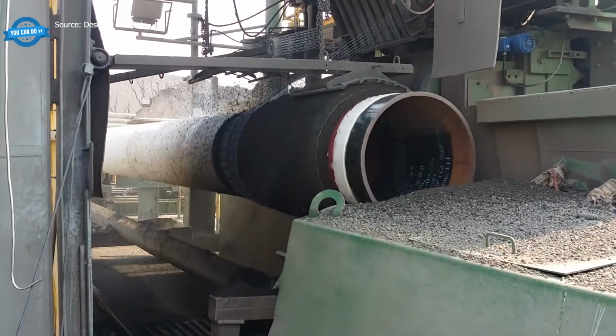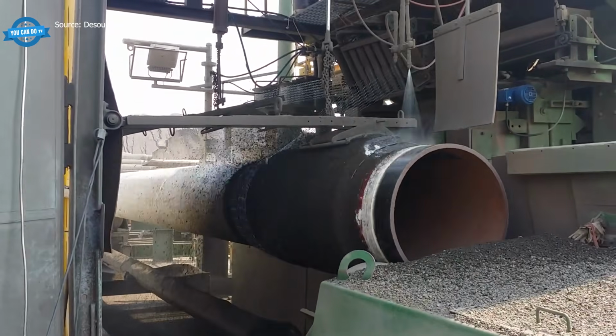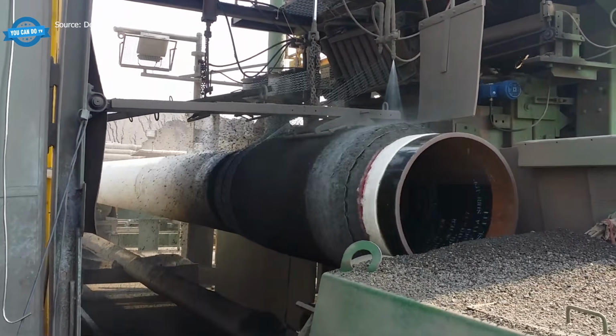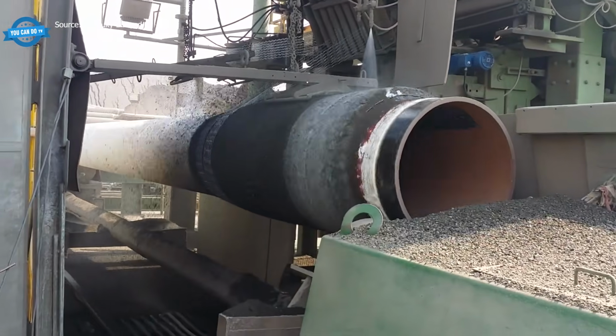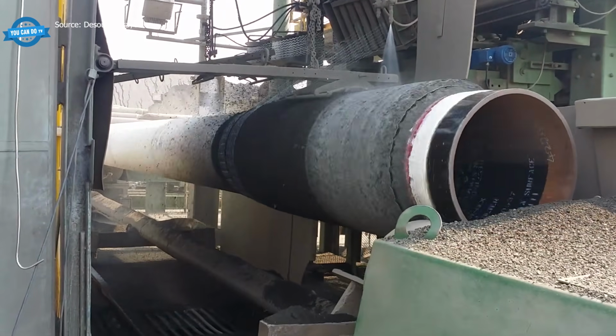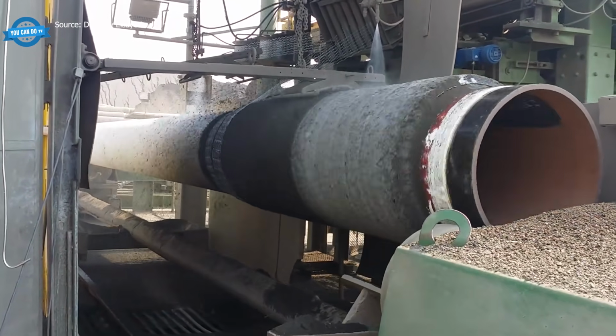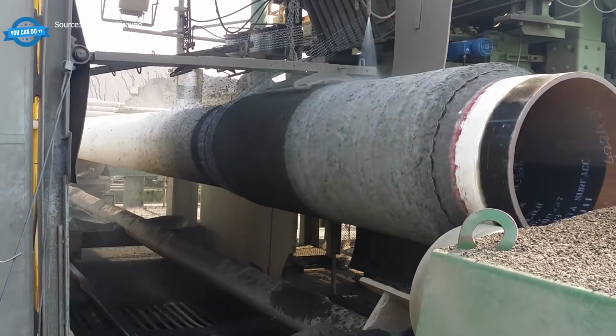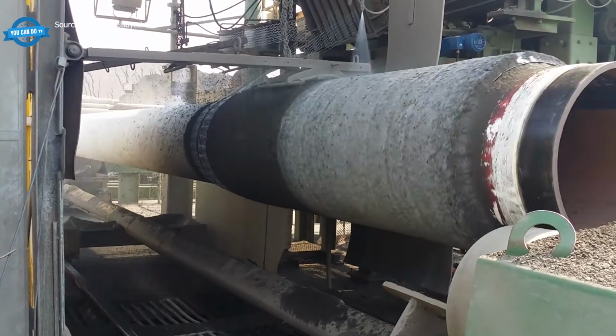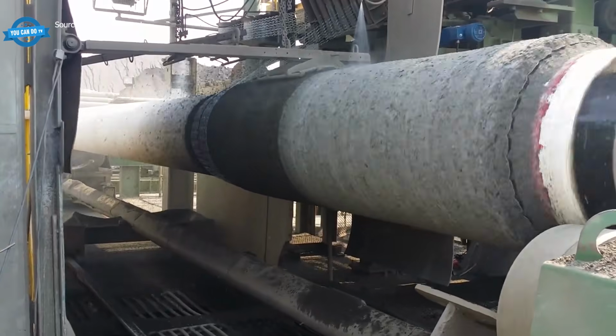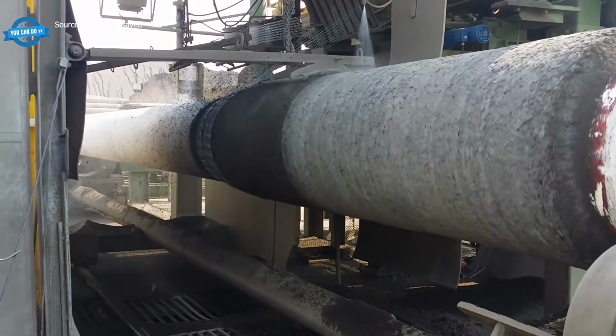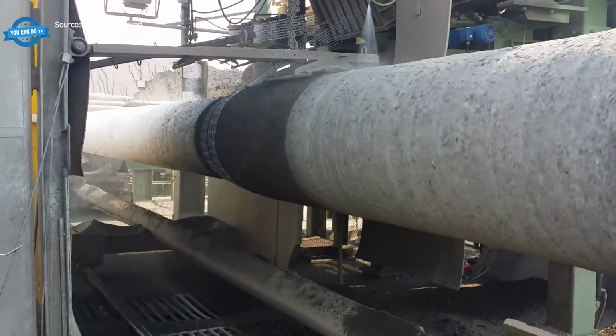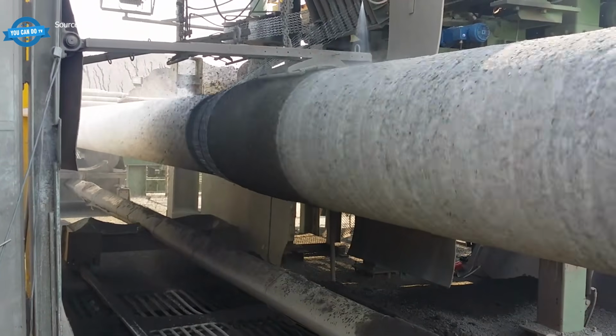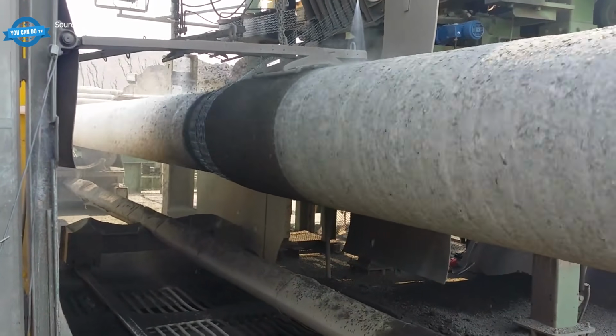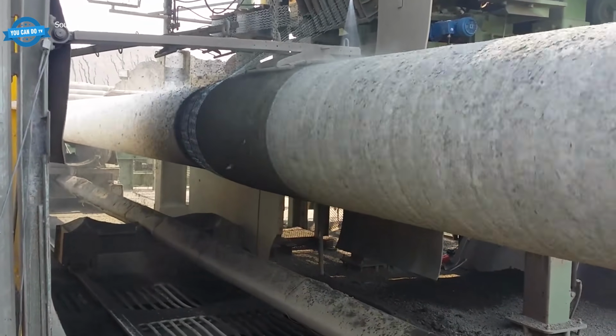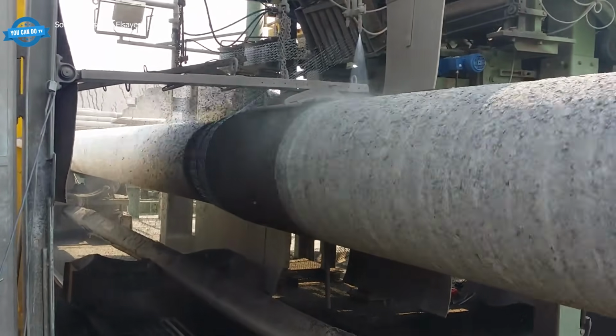The most visible layer is concrete weight coating, or CWC. A bare steel pipe entering the coating plant already carries an anti-corrosion primer underneath. It enters a rotating, advancing roller system where a continuous stream of high-density concrete is sprayed onto the rotating surface at high pressure. At the same time, a steel mesh reinforcement and a tight outer wrap are fed in parallel, embedding into the concrete as it builds up and locking the coating mechanically to the pipe.